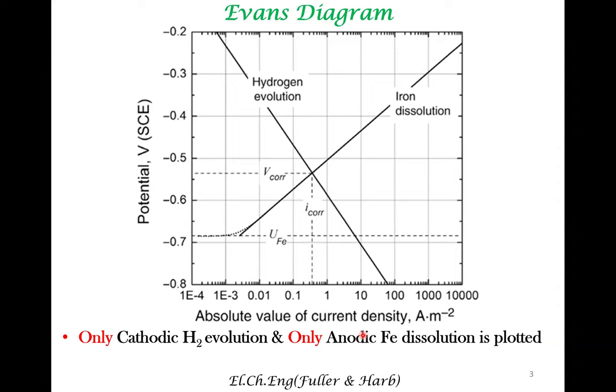But as we emphasized in the previous lecture, what is of significance is this quantity, V corrosion. This corrosion potential is the potential of the metallic sample that is getting corroded, at which the rate of generation of electrons via the anodic reaction, that is the corroded sample, is equal to the rate of consumption of electrons by the reduction reaction, which in this case is the hydrogen evolution reaction. So the significance of a corrosion potential is not at all different in this representation. And once you get the corrosion potential, corresponding to that is the corrosion current. And the corrosion current is a measure of the rate of corrosion.